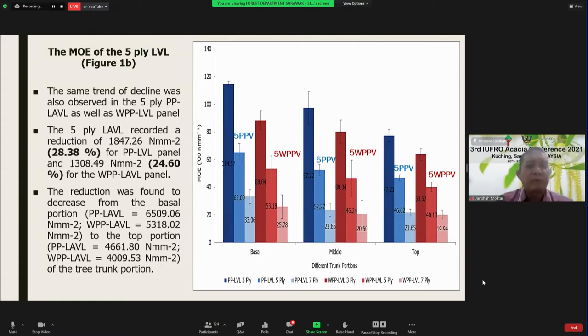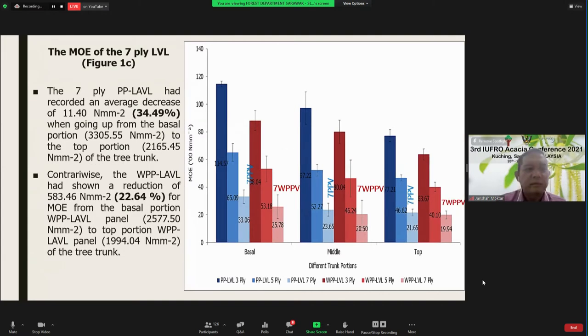Meanwhile, for the MOE of the 5-ply LVL, the same declining trend was also observed in the 5-ply prepressed veneer LVL as well as the without prepressed veneer LVL panel. The 5-ply LVL recorded a reduction of 1,847 newton per millimeter square for the prepressed laminated veneer lumber panel and 1,308 newton per millimeter square for the without prepressed LVL panel. The reduction was found from the basal portion to the top portion of the tree trunk. Next.